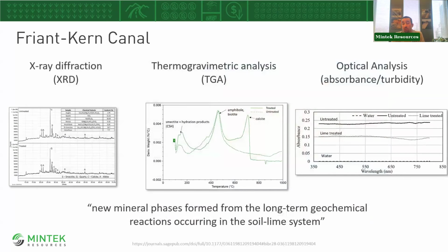Just with that, you thought we were done being overly technical. This is a pretty cool slide, though, I must say. XRD, X-ray diffraction, is a technique we use in the lab to identify different crystalline structure materials. So in lime stabilization, XRD can help us determine mineralogical changes and the formation of new compounds. This XRD pattern showed that the lime treated soil indicated the presence of different minerals like calcite, but also the absence of others like smectite, which is the expansive clay we were battling at the start.